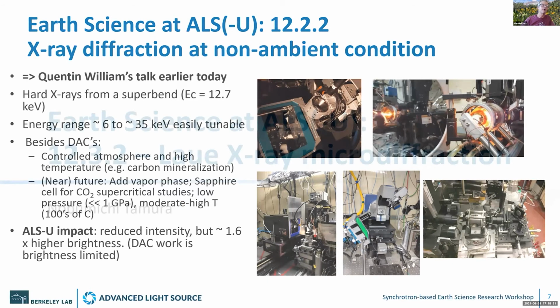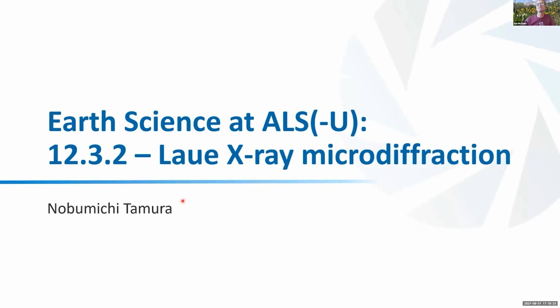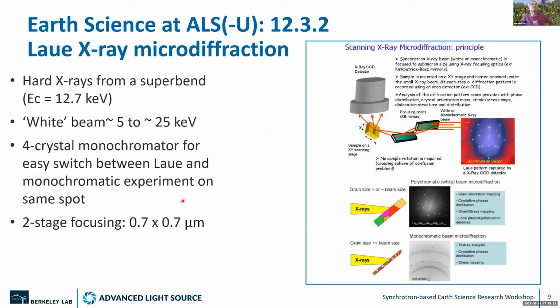Next, I want to talk about the ALS's Laue X-ray microdiffraction program, which is operated by Nobumichi Tamura on beamline 12.3.2. 12.3.2 draws its X-rays from the same superbend as 12.2.2. It has slightly different primary optics. It has a white beam with an energy range from 5 to 25 keV. This white beam is focused by a KB arrangement onto a submicron spot on a sample that is in reflecting geometry with the detector at very high angle.